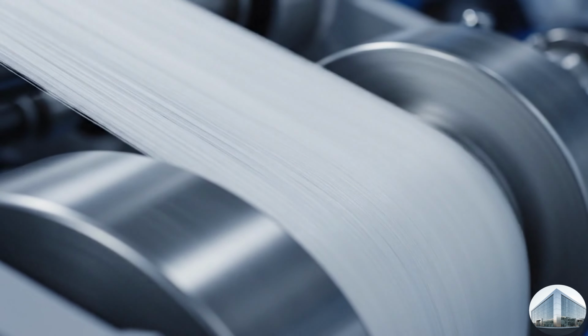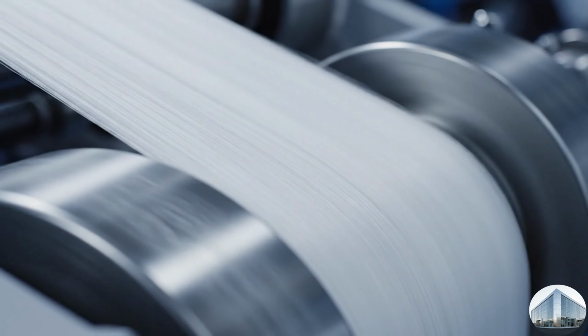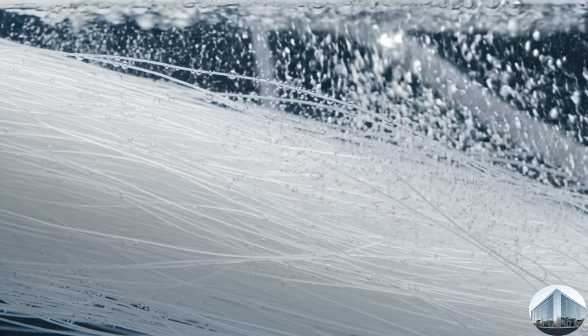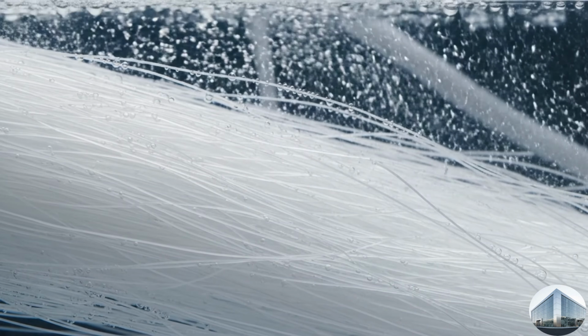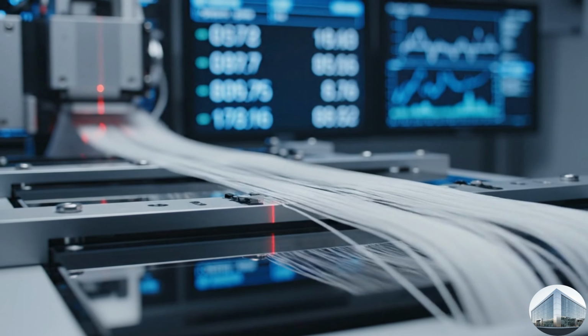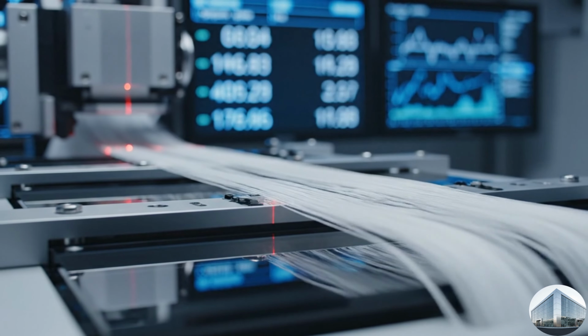Purity is paramount. The fibers pass through a specialized chemical cleaning system to remove every microscopic impurity, preparing the polymer for its dramatic transformation in the thermal chambers. Advanced sensors monitor every micron of the process. In this high-tech environment, consistency is the key to creating a material that can survive the vacuum of space.